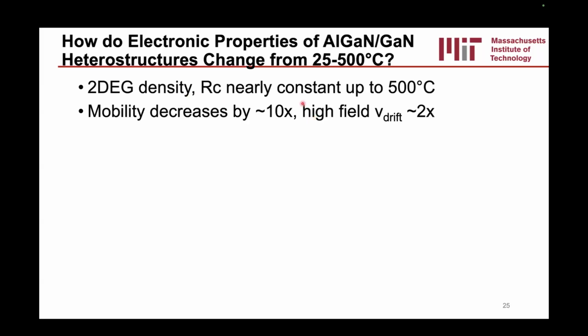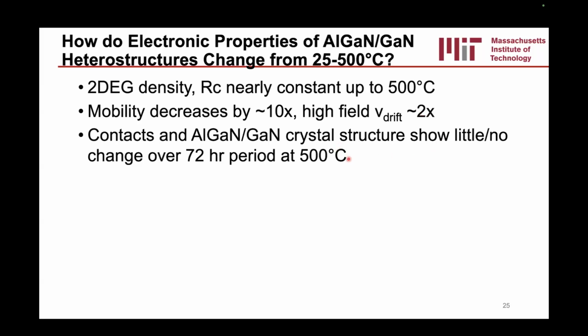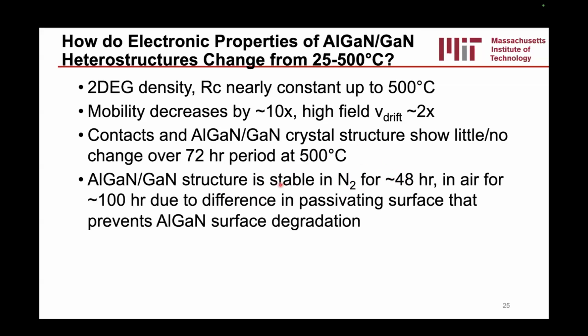All right, so just to sum up this portion here, what did we learn about high temperature properties of AlGaN/GaN heterostructures? We learned that the 2DEG density and the contact resistance are roughly constant up to 500 C. We've learned that the mobility decreases a lot, 10x, but the high field drift velocity decreases maybe around 2x or so. We've learned that the contacts seem pretty solid, at least without bias, and over a 72-hour period at 500 Celsius. And we've learned that the structure is more stable in air than in nitrogen, mostly because of the surface degradation. It happens worse in nitrogen environments.